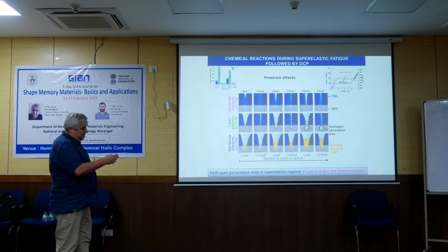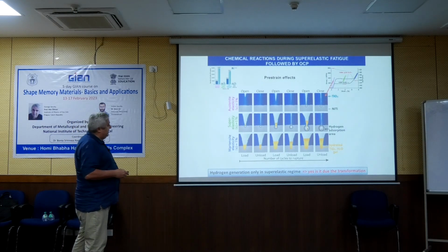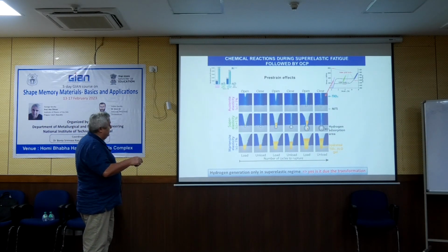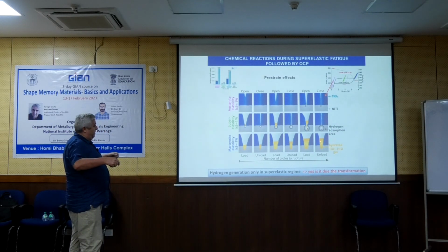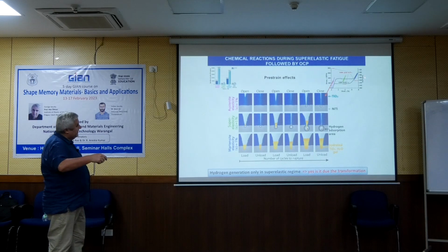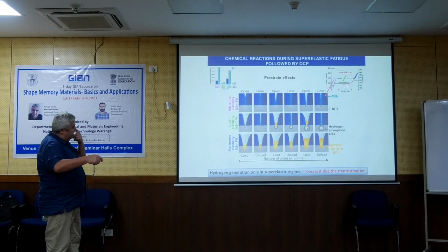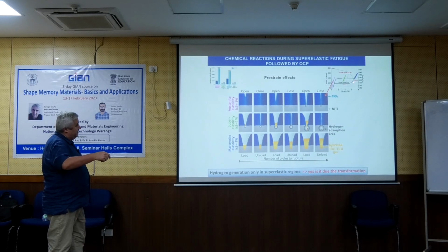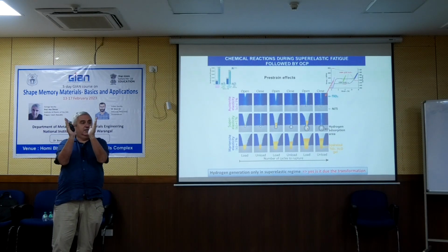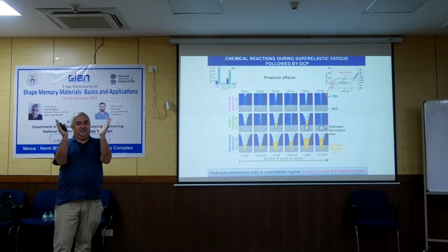In the elastic range, the surface oxide is cracking only at the end of cycling. In the beginning, there is very little damage. So the OCP remains high. In case of martensite, we have fully stretched the wire, but then upon unloading, we never go back with the strain, because we keep this pre-strain and cycle. So the cracks remain open and thus only do like this. So the passivation proceeds and it never breaks.